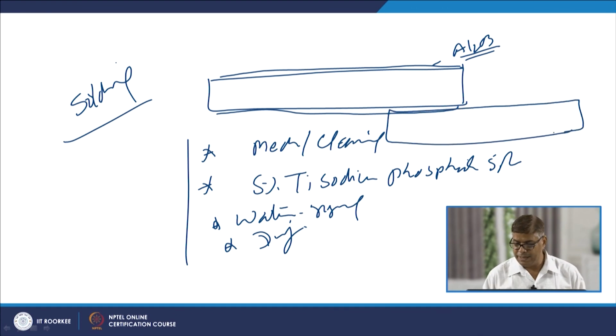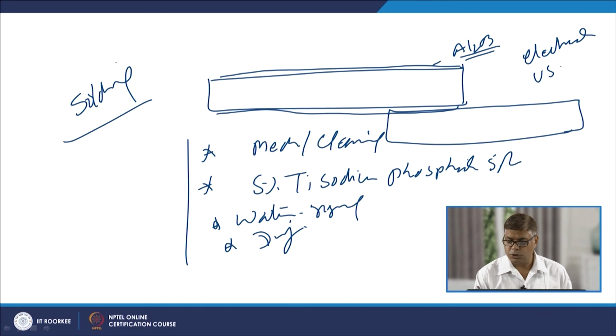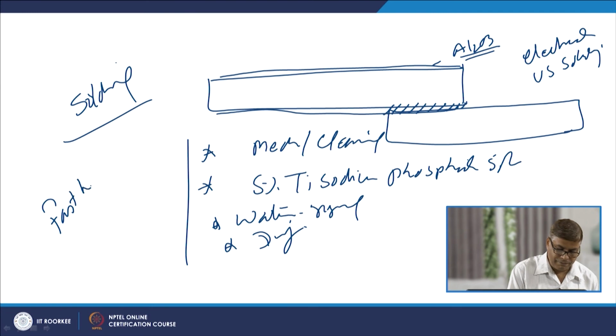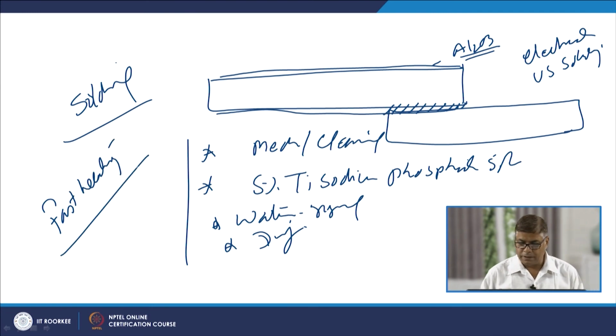Very high speed heating methods are used, like electric or ultrasonic soldering irons, providing the required faster heating, so that the aluminum does not get time to get oxidized during the heating. So, the main idea here is to apply faster heating methods, so that the required soldering temperature can be realized quickly, and suitable solders can be used to develop the joint at the interface. So, cleaning is basically key in aluminized steel soldering, thereafter faster heating and then application of the solders for developing the soldered joints.